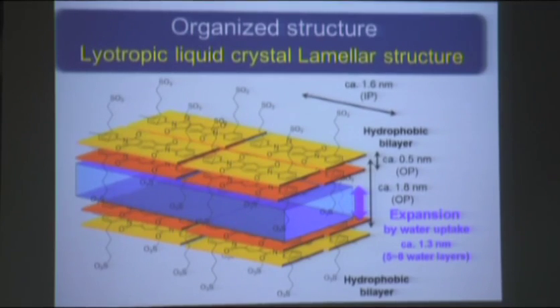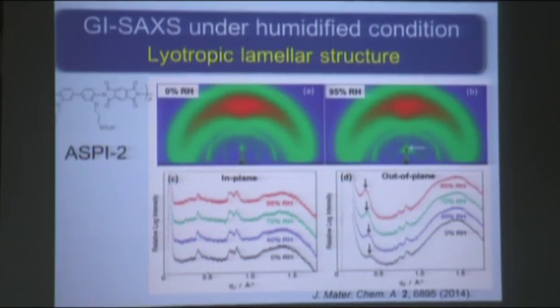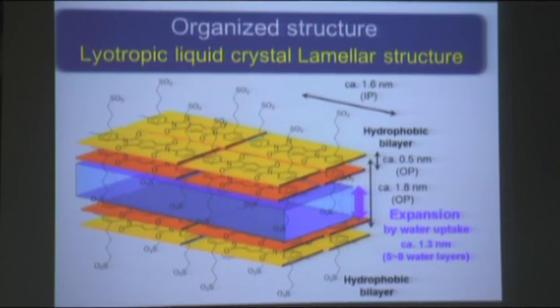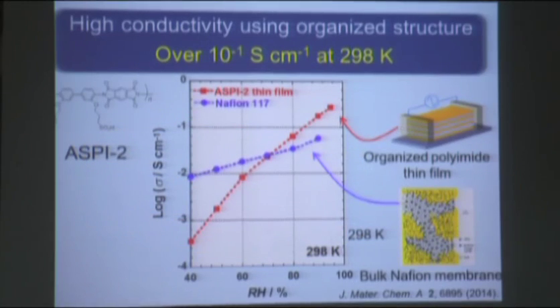So this means that as the humidity increases, the water comes inside of this polymer, so that the water can enter here, then expand this direction. So the changing value corresponds to this expansion, so that we can see the 1.3 nanometer very thin nanochannel for proton transport. Okay, so here is the proton conductivity investigation. You see the humidities. This is the proton conductivity. The blue one is the Nafion. This is the conventional Nafion fuel cell membrane. So fortunately, the red one has a very high conductivity compared to this Nafion. So this is the first to demonstrate how organized structure contributes to proton transport properties.